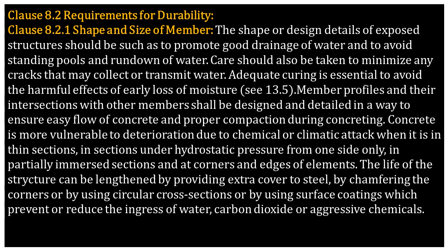See 13.5. Member profiles and their intersections with other members shall be designed and detailed in a way to ensure easy flow of concrete and proper compaction during concreting. Concrete is more vulnerable to deterioration due to chemical or climatic attack when it is in thin sections, in sections under hydrostatic pressure from one side only, in partially immersed sections and at corners and edges of elements. The life of the structure can be lengthened by providing extra cover to steel, by chamfering the corners or by using circular cross sections or by using surface coatings which prevent or reduce the ingress of water, carbon dioxide or aggressive chemicals.